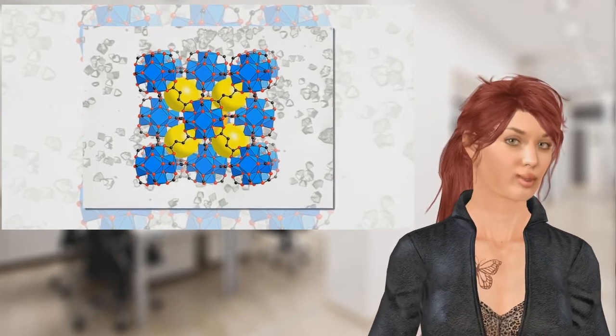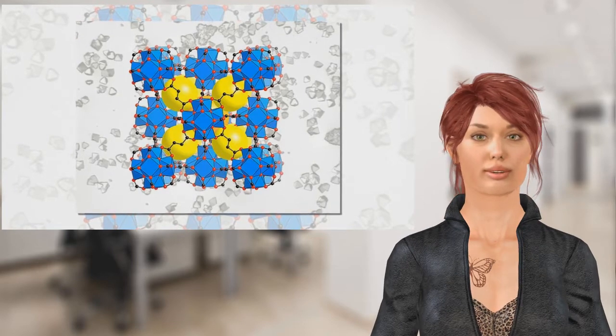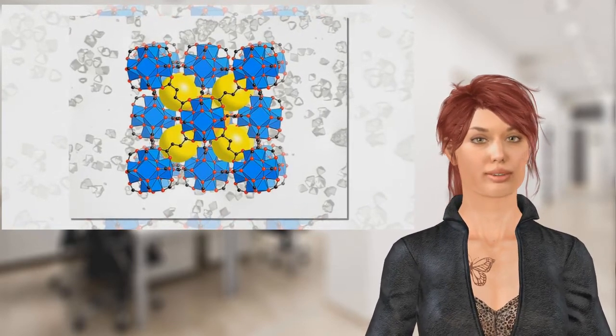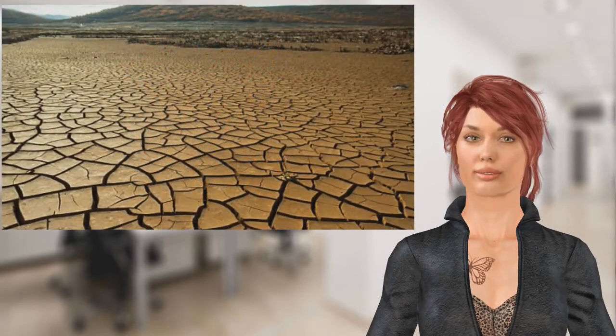X-ray diffraction studies have shown that the water vapor molecules often gather in groups of eight deformed cubes. Sunlight entering through a window heats up the MOF and drives the bound water toward the condenser, which is at the temperature of the outside air.